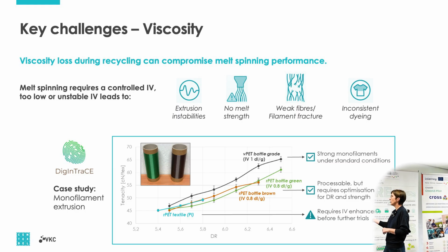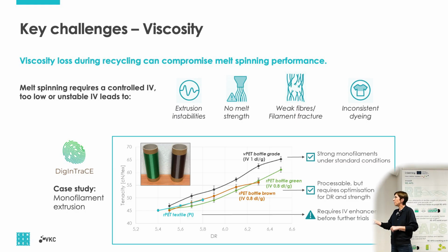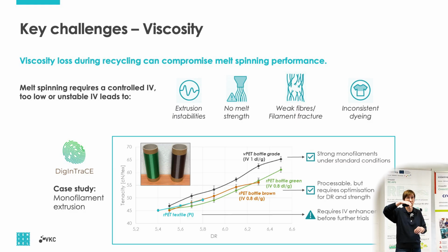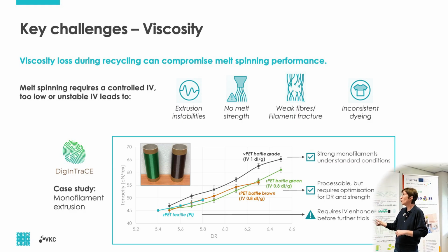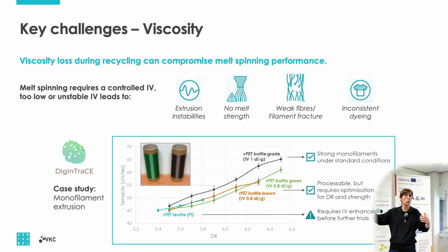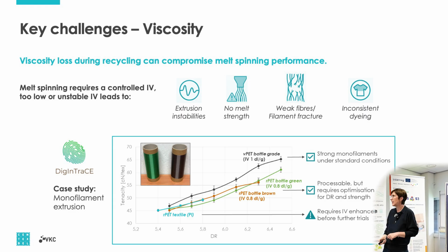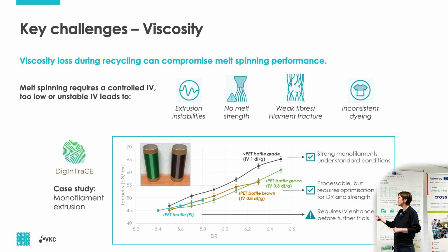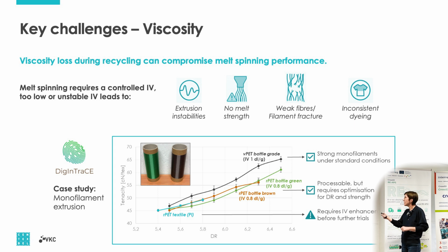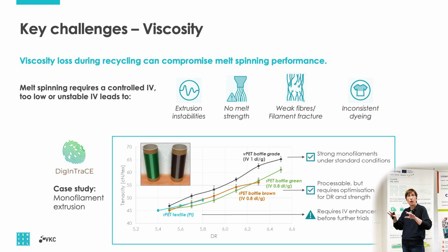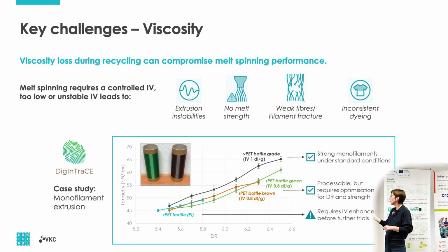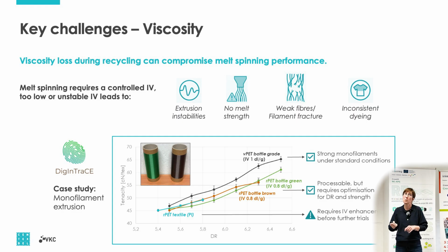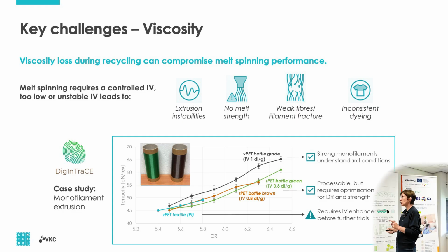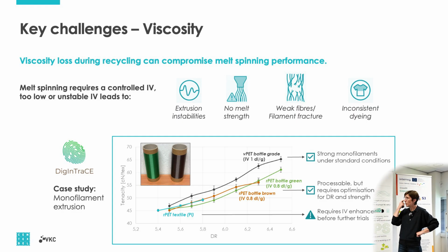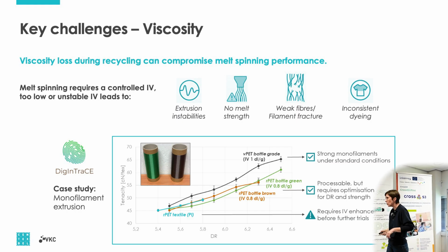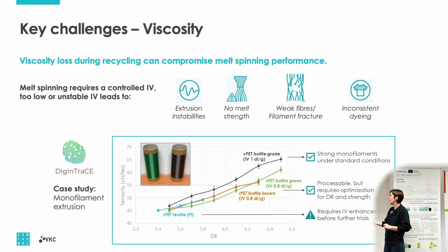Things like this. You can say, yeah, I have problems, my extrusion is unstable because you have a lot of variation in your viscosity. You are losing your melt strength because you're losing your long chains, so you don't have any strength in your material. Filament fractures, and this may be underestimated, but if you have different polymer chain lengths and you try to dye those materials, you can have uneven dyeing. Just to show you an example from a European project where we worked with monofilament extruders.